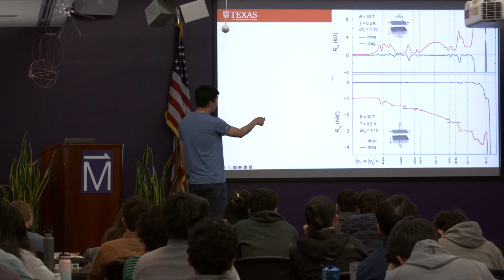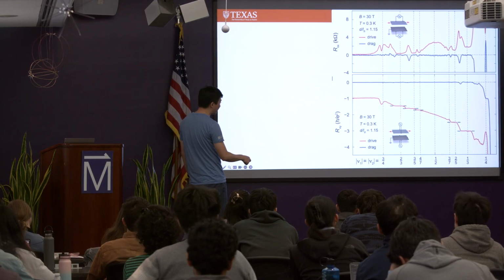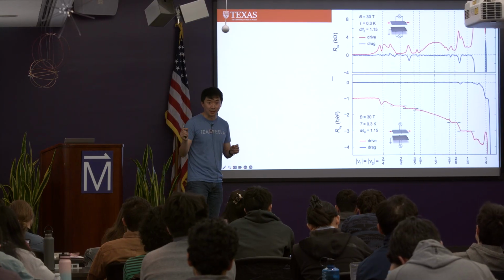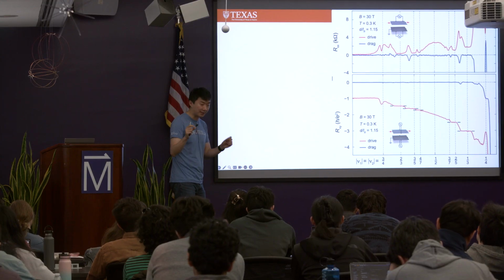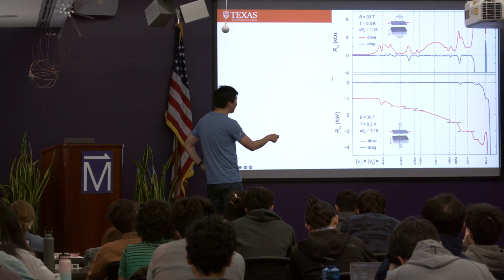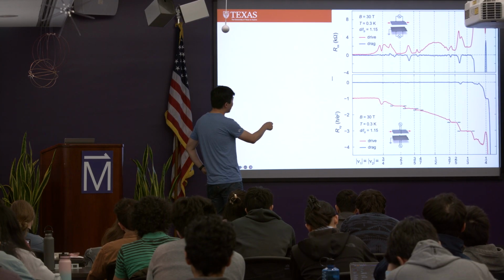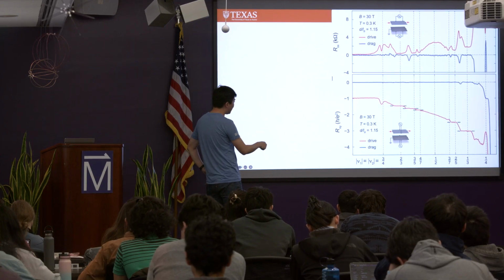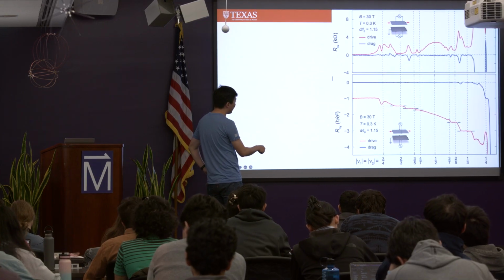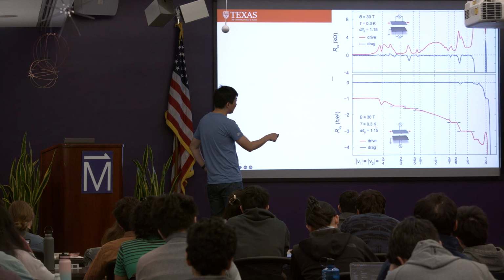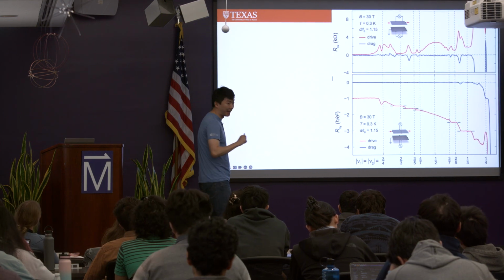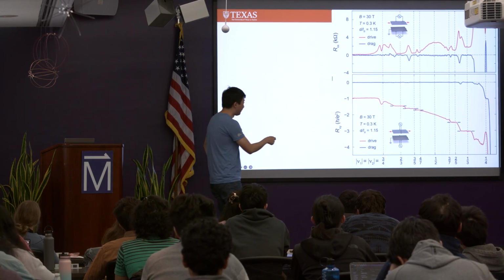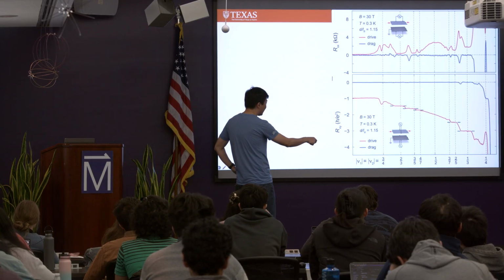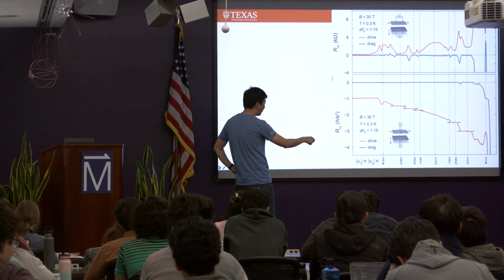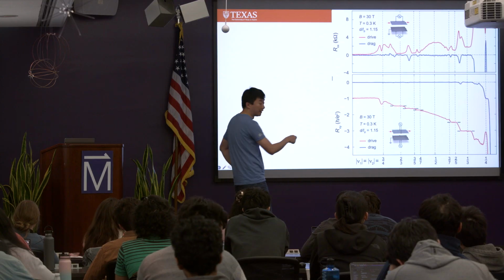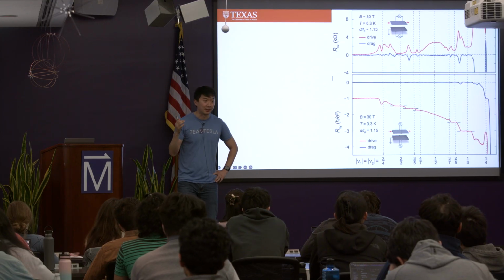So we're working with the Hall-bar data. We're sweeping density along the equal density line, meaning that each layer filling is fixed to be the same, right? And the red data, the top channel is longitudinal resistance, bottom channel is Hall resistance. Red is measured from the drive layer, and blue is the passive drag layer, right? From the drive layer, you can see that you're getting all these plateaus. You get 1/3, 2/5, 3/7, right? And then 2/3 here, right? So the sequence looks like a single layer state.